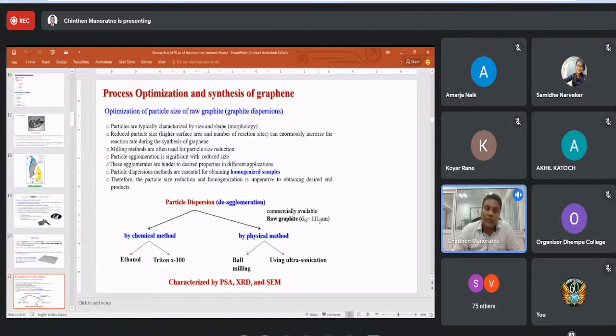So therefore, one of the objectives during our study is to optimize this particle size dispersion, or simply say, break these agglomerates or clusters. So we approached two methods: one is chemical and the other is physical. For the chemical method, we use ethanol and Triton as a solvent, or maybe Triton as a surfactant. For the physical method, we use ball milling and ultrasonic vibration. And we try to optimize the particle size for our production of graphite oxide and finally graphene.